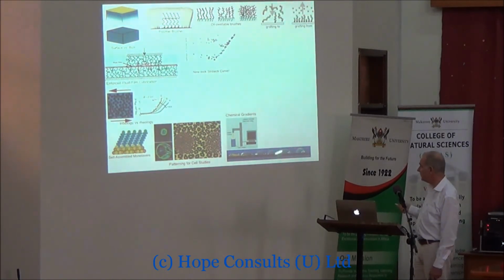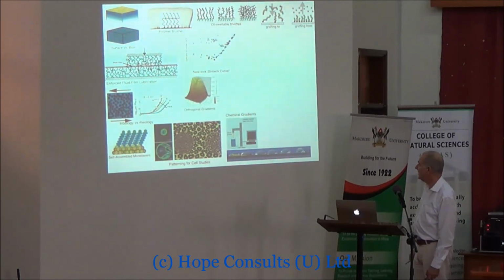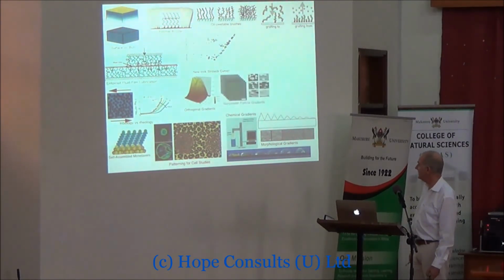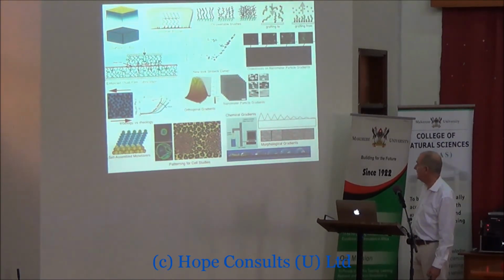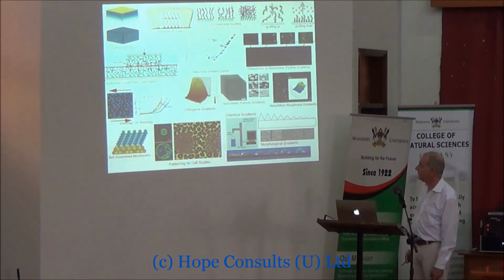Then I talked about chemical gradients, how we can functionalize the surface with different wettabilities, which can be used for a number of different purposes. And we can functionalize them also orthogonally to look at two effects at once. And then morphological gradients on the micrometer scale, on the nanometer scale, and how we can use those to look at cell behavior as a function of roughness. And finally, I talked about how we can combine nano and micrometer roughnesses to look at their synergistic effect on cell integration.